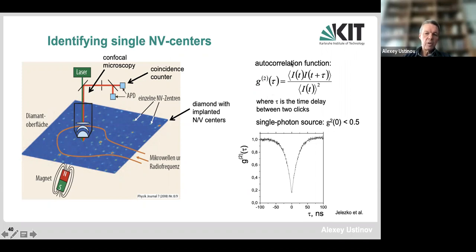And that means that the autocorrelation function, which we measure, will depend on the time delay between the clicks. And if the delay is 0, then there will be no correlation at all. Basically, this means that there will always be one detector clicking or the other. However, if the delay is longer than a particular time, which is associated with the propagation path and also the intensity of the source, then the function actually goes to 1, and there will be independent clicks of those detectors. So a single photon source can be recognized if this autocorrelation function squared is smaller than 1/2. And this is real data from the paper of Fyodor Zhelezko many years ago, showing that this is really a single photon source fluorescing from an atomic scale defect.